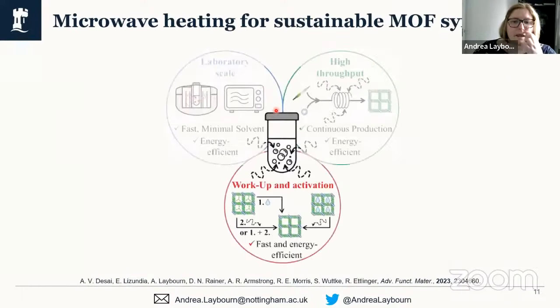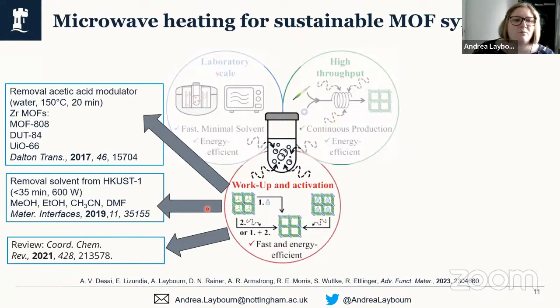So I want to now touch on a couple of examples in the literature where microwaves have shown excellent promise for the workup and the activation of metal organic frameworks. So I've got an example where a team has looked at zirconium MOFs, where the acetic acid modulator coordinates into the MOF structure, and this could be removed by essentially heating up the materials in water, and the acetic acid then dissolves in the water, removing that coordination with the zirconium.